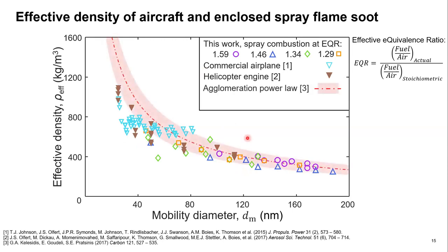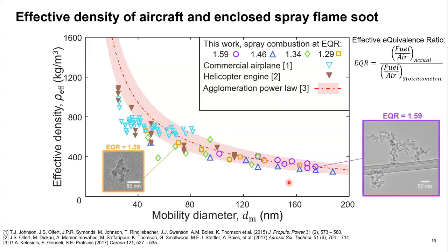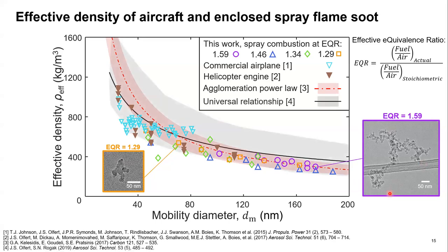We can further understand what this tells us by comparing to the theory once again. Here the line represents the agglomeration power law for agglomerates with a primary particle size of 14 nanometers, and the shaded area represents the variation in primary particle sizes that we observed in our data. As we can see, the agglomeration power law describes our data quite well, and we see this characteristic drop in the effective density when we go from small mobility diameters to large mobility diameters. This is expected, of course, because at small mobility diameters, we have small particles with just a few primary particles, and there's not a lot of empty space in the mobility diameter. At high mobility diameters, we have these large fractal agglomerates, which have a lot of empty space, thus lowering the effective density.